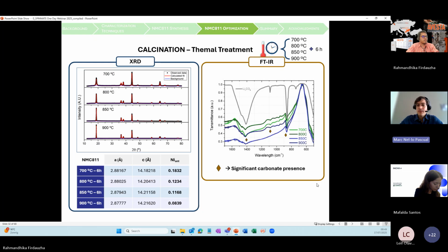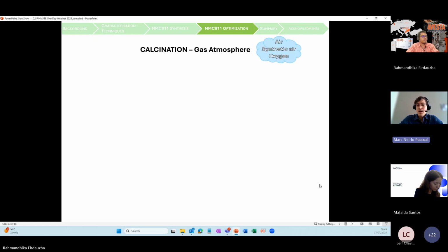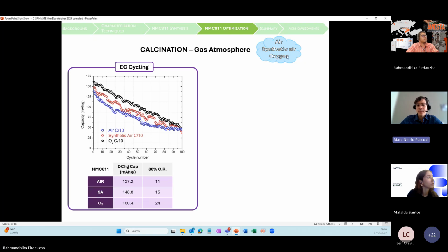So if you go to the next slide, for that, we considered 2 atmospheres. One is synthetic air, which is the same as air, but we are removing the CO2 from this atmosphere. And the other was oxygen, which also doesn't have any carbon dioxide, but we also go for a more oxidative atmosphere, where the idea is to reduce the amount of nickel 2+ in the samples, to go for a fully oxidized material and try to reduce the number of nickel 2+ ions that are the ones that swap with the